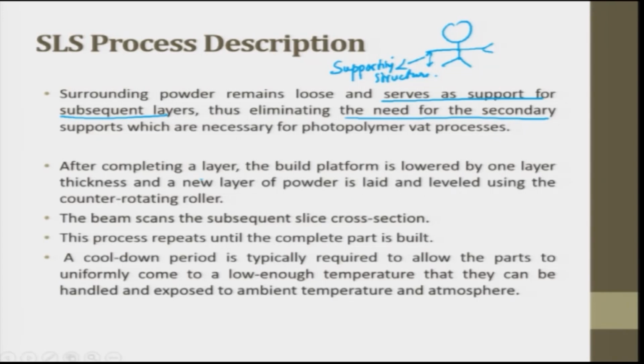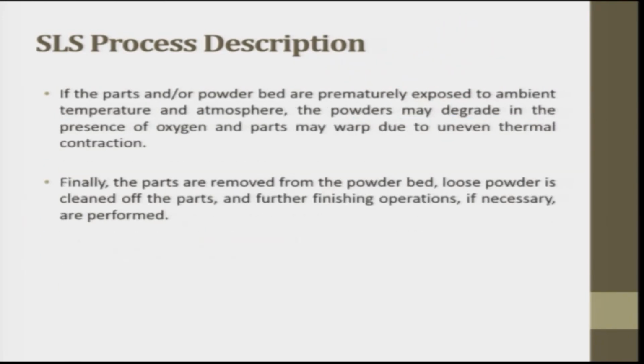After completing a layer, the build platform is lowered by one layer thickness and a new layer of powder is laid and leveled using the counter-rotating roller. The beam scans the subsequent slice cross section. This process repeats until the complete part is built. A cool down period is typically required to allow the part to uniformly come to a low enough temperature that it can be handled and exposed to ambient temperature and atmosphere. If the part or the powder bed are prematurely exposed to ambient temperature and atmosphere, the powder may degrade in the presence of oxygen and the parts may warp unevenly.